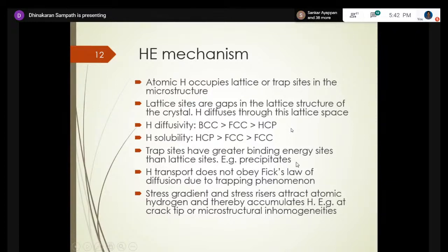So traps have greater binding energy than lattice sites. For example, some second phase particles will hold more hydrogen. That means it will accumulate more hydrogen in that location. And we'll see some mechanisms which tend to weaken the location because of the trap sites. And also they are sometimes beneficial. So that's the trick.